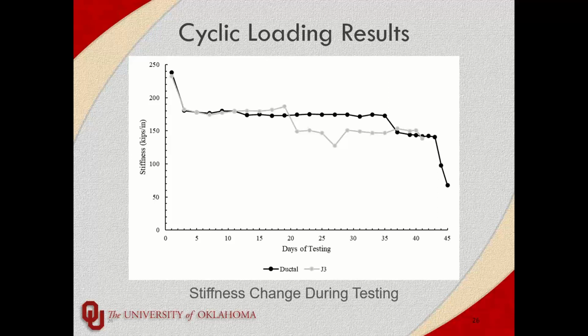And so we increased the load. As soon as we increased the load on the Ductal slab, you see that it goes to about the same level as J3, which sort of shows that, at least what I think, had we not previously damaged the J3 slab in the middle of the test, it would have been a very similar trend as Ductal had, which I thought was great. But one good thing is post that we did fall within the FHWA limits for fatigue failure once we increased the load, and Ductal actually extended that quite a bit farther for a couple of days.